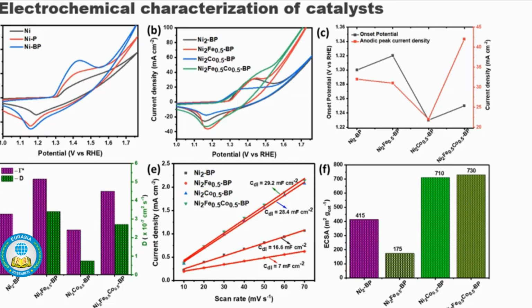The other one shows that after adding cobalt, the overpotential shifted to the more negative side, and after adding iron to the nickel composite, the current density increased, and this shows that the addition of the iron and cobalt elements changes the nickel surface properties as well as the kinetics of the surface, and the electrolyte and intermediates interaction. Now, with nickel species being the most active sites of the catalyst, the onset potentials of the anodic scan of methanol and urea can be estimated to be close to that of nickel 2 and nickel 3 oxidation.